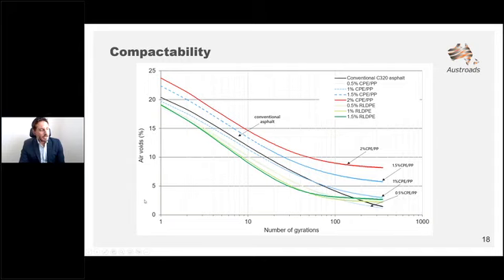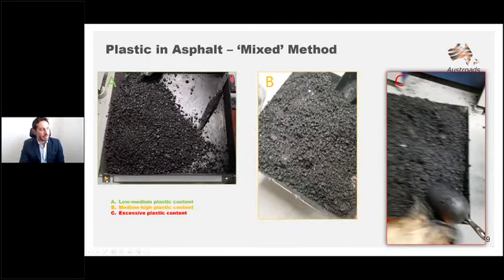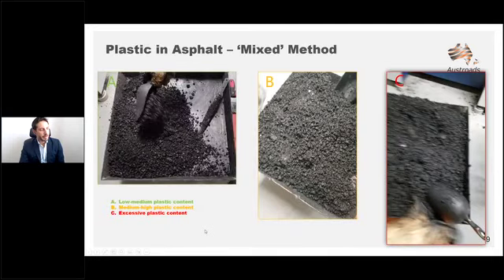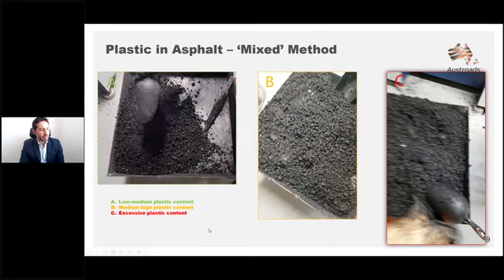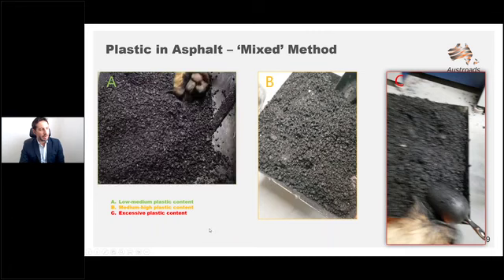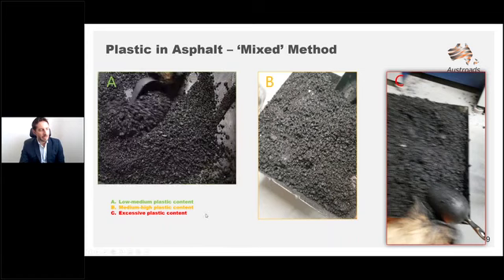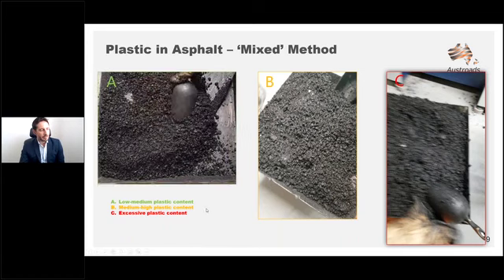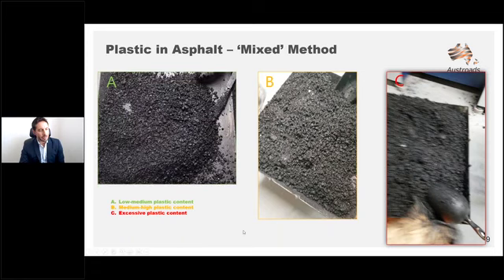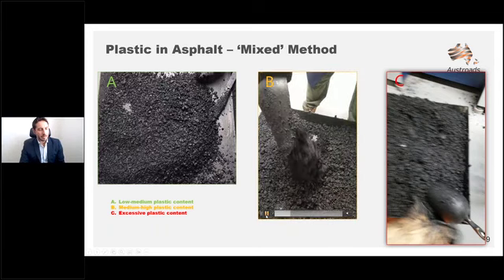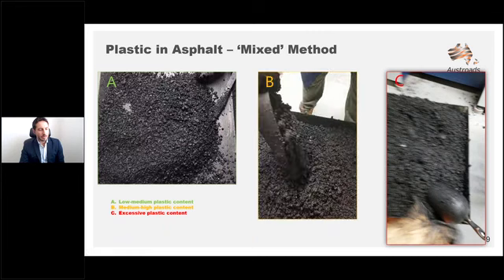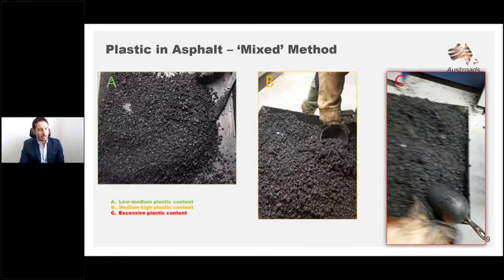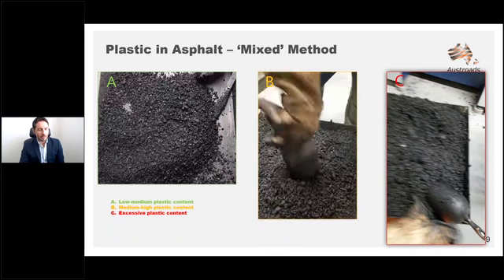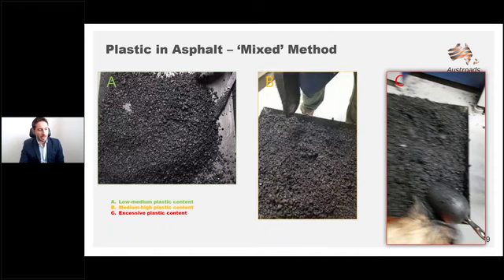Now, this is a very quick example of how different mixes are at the end of the manufacturing process. So the video that is running now is related to a low to medium plastic content. And you can see that it's quite flowable and workable, and it was very easy to compact. When you start adding more plastics, you will see that it becomes increasingly more difficult to work with and to handle. Still workable, but obviously more effort is needed, and that will translate in more compaction effort to achieve the void contents in the field.